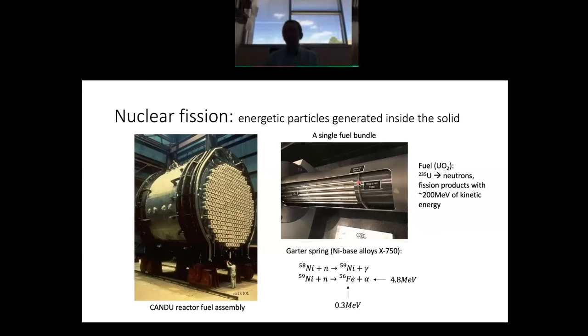And nickel, if you subject it to thermal neutron irradiation, will undergo a series of transmutations where it goes from the naturally abundant nickel-58 to nickel-59, and then the nickel-59 absorbs one more neutron and decays to iron-56 and emits an alpha particle in the process. The iron recoils at an energy of about 300 kiloelectron volts, and the alpha particle has almost 5 megaelectron volts. So if you look at the dose that little Garter Spring gets, it's about twice as high as the dose that it would have gotten from the neutrons alone, right? So all of these materials are continually self-irradiating from the inside, generating these high energy particles.